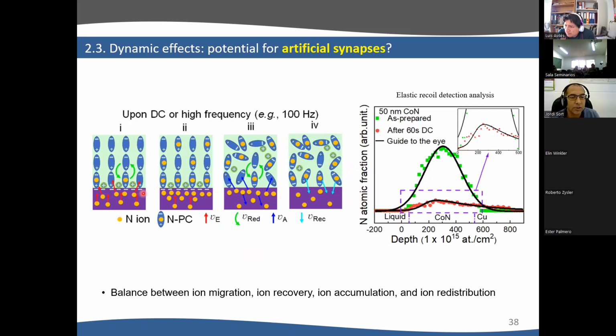But in order to release this nitrogen to the liquid, to the propylene carbonate, one of the steps that needs to happen is that the propylene carbonate chains are able to solvate, to absorb the ions. Only if this is possible, the nitrogen can go away from the film and the magnetization increases. We think that if you go too fast, and for thin layers, there is nitrogen accumulated here, and somehow the propylene carbonate chains become saturated with nitrogen. The nitrogen cannot go out simply because there are no more free chains.